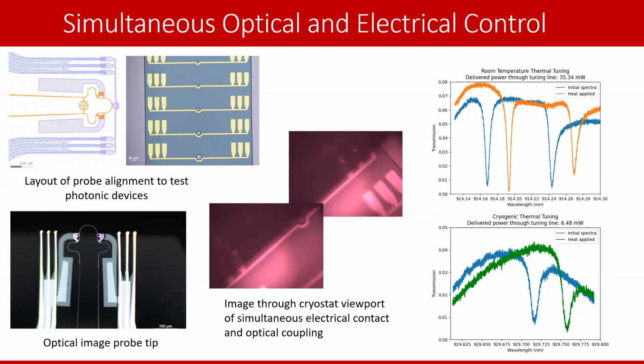So this here is an example of an extremely simple photonic device. This is just a whispering gallery mode resonator with a patterned gold wire next door. This is a 4-point probe measurement, which means you literally just run some current. You can measure the voltage. It gives you the resistance. And as a result, you can just thermally dump some heat into this resonator. The heating of the silicon carbide will cause the refractive index to change.